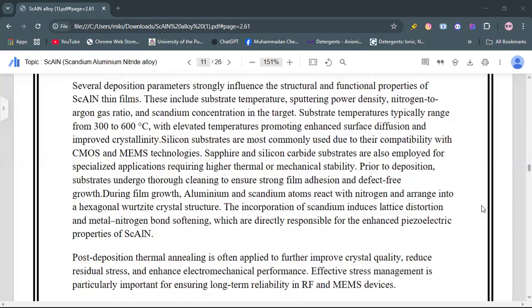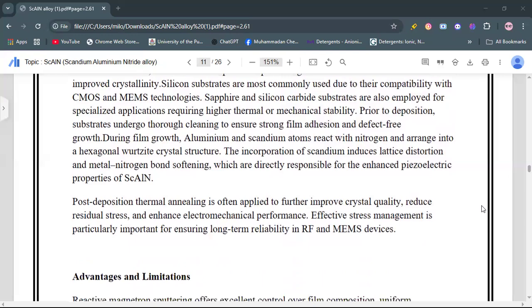During film growth, aluminum and scandium atoms react with nitrogen and arrange into the hexagonal wurtzite crystal structure. The incorporation of scandium into the aluminum nitride lattice distorts the lattice and causes metal-nitrogen bond softening, which are directly responsible for the enhanced piezoelectric properties of the scandium aluminum nitride alloy. Post-deposition thermal annealing is often applied to further improve crystal quality, reduce residual stress, and enhance electromechanical performance. Effective stress management is particularly important for ensuring long-term reliability in RF and MEMS devices.